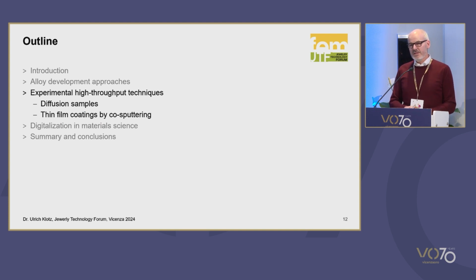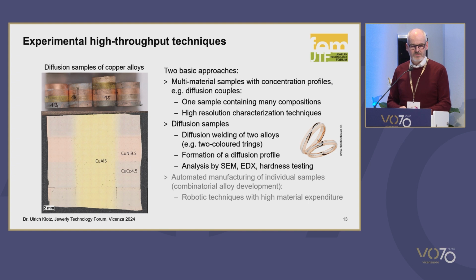Now, often simulation is not working as well as we would like, because we are lacking experimental data, because every simulation tool is usually based on experiments. So when we want to make experiments, it's good to also use screening methods, because doing one alloy after the other is a lot of time and a lot of money. But screening techniques are based on samples that show inside the sample a certain composition range. And within one sample, we can characterize many alloys without making 20, 50, hundreds of samples. And there are two techniques that I would like to show that are used.